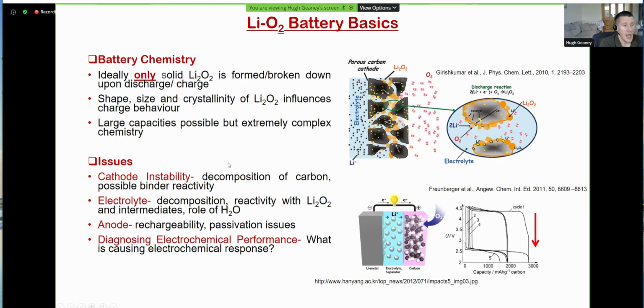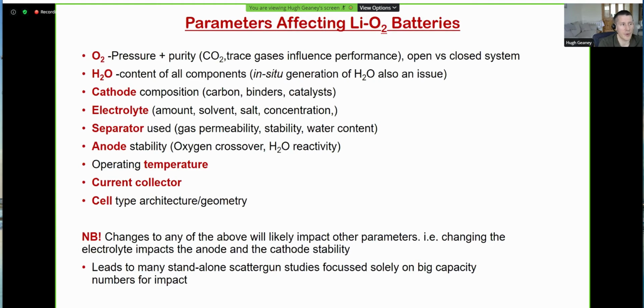So there's lots of issues with it. We have cathode instability, we have electrolyte instability, anode instability, and actually even diagnosing what the performance is due to. So you can have almost phantom reactions where you have side reactions that completely take over your cell. So again, to briefly touch on the different parameters, you can look at the oxygen supply in terms of dictating the performance. So we have the pressure and purity, with water content, which is really key, with the cathode composition, with the electrolyte composition, the separator that's used.